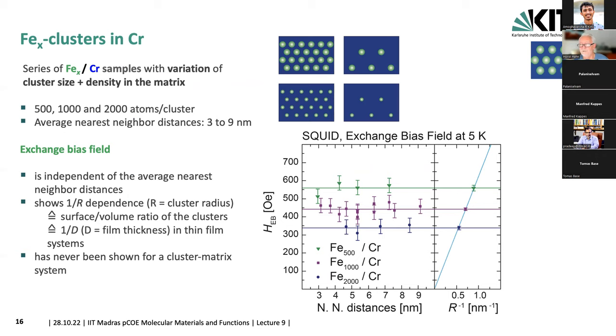We did a series of iron clusters in chromium with a variation of the cluster size and also the number of clusters in the matrix, so the density or volume fraction. And here are the sizes, 500, 1,000, 2,000 atoms per cluster. And then it's, of course, a certain size distribution which we obtain over here. And then, depending on the volume fraction of clusters which you put in there, you get different nearest neighbor distances between the ferromagnetic clusters. So depending on the volume fraction, we get a 3 to 9 nanometer spread. If you put a large fraction of clusters in there, then you are more in this situation here, where the clusters are 2 to 3 nanometers apart. And in the other case, they are 9 nanometers apart when the volume fraction is smaller.